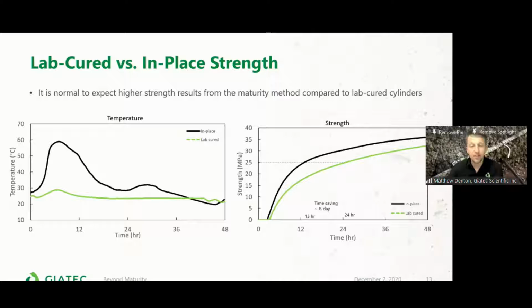On the left-hand side, we have a graph showing the in-place concrete strength versus your lab cured sample. So what's happened here is they've taken a sample on site, put that into a cube, and sent that to the lab after 24 hours, and that's cured at a constant temperature of about 20-25 degrees, which is fairly standard practice. Whereas on site, this was a particularly warm climate where the sample was taken. You can see that the spike in temperature in the first 12 hours was much greater on our element on site. In this particular scenario, it was a slab that was poured.